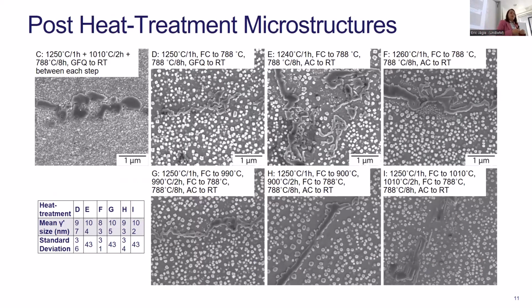intergranular microstructures. So I'm going to ignore the first two that didn't recrystallize for the rest of the talk. I'm just going to concentrate on the microstructures of the rest. So the first heat treatment C, which was basically recrystallized, the two-step aging as normal, and then gas fan quench, so quick quenching from temperature. You can see a very, very fine structure for the gamma prime, and then we have carbides along the grain boundaries. So that was the one that was mainly different, just because it was the only one that we quickly cooled. Everything else has equivalent furnace cools.